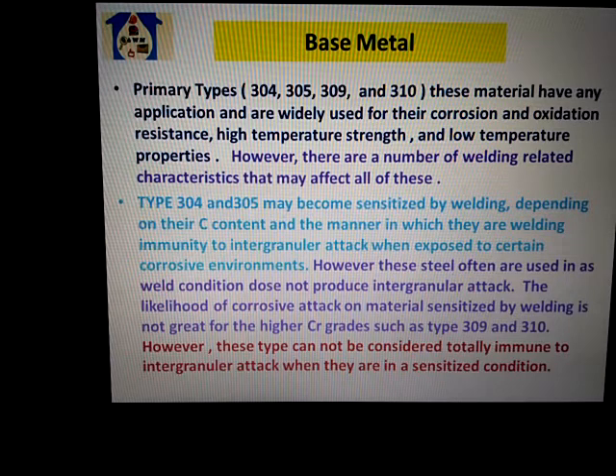Types 304 and 305 may become sensitized by welding, depending on their carbon content and the manner in which they are welded, losing immunity to intergranular attack when exposed to certain corrosive environments. However, they still often are used in the as-welded condition, which does not produce intergranular attack. The likelihood of corrosive attack on material sensitized by welding is not great for the higher chromium grades such as types 309 and 310. However, these types cannot be considered totally immune to intergranular attack when they are in a sensitized condition.